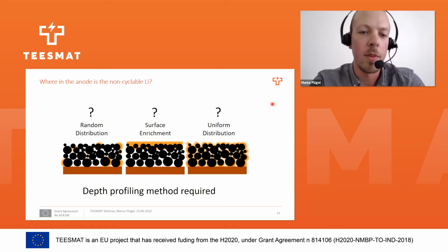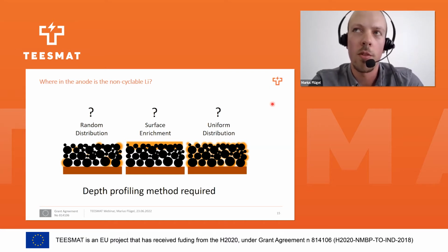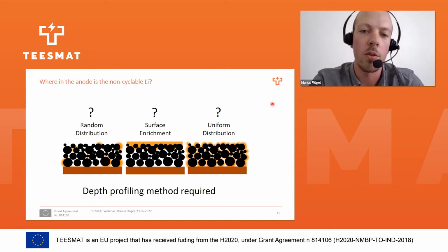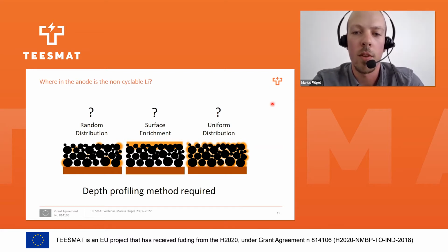Why do we need a depth profiling method like GD-OES? For most methods, it's not possible to create depth profiles of our samples and also to quantify, for example, lithium. There are some techniques, for example, XPS sputtering, but the sputtering rate of this technique is very low. And with GD-OES, we can sputter through a whole electrode within a few hours.